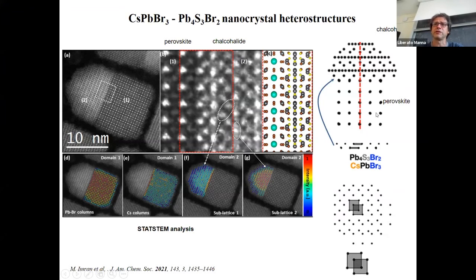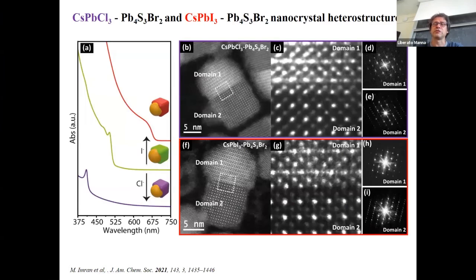So there is a perfect epitaxial match along this direction. Now, this perfect epitaxial match generates this very nice epitaxial heterostructure. We also tried to perform an ion exchange on these heterostructures. And interestingly enough, although quite expected, an ion exchange occurs only in the perovskite domain. So the chalco halide domain remains bromide in composition from the point of view of the halide. And the two new heterostructures are completely epitaxial.